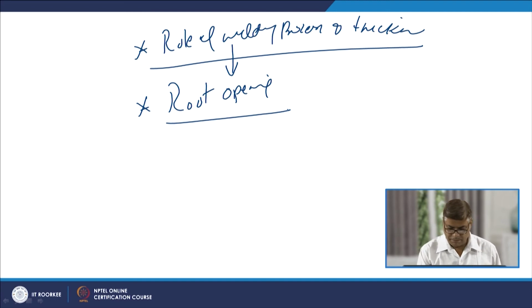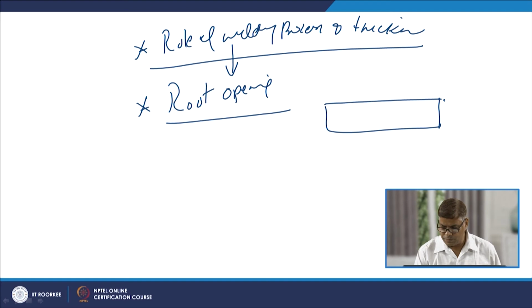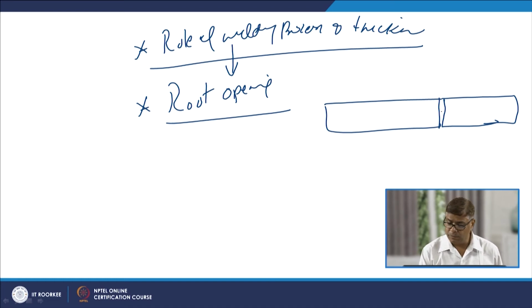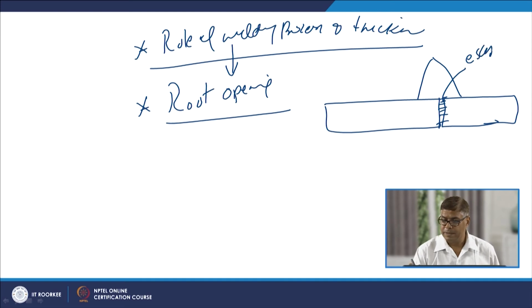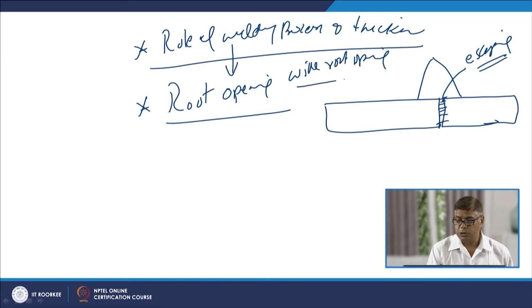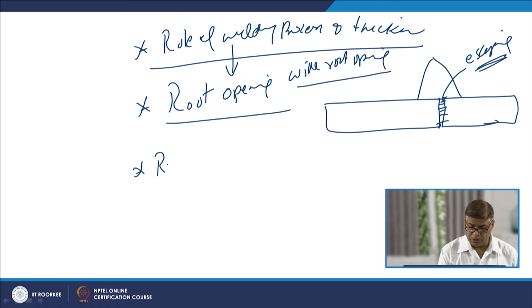This is important because if the gap is very small, then whatever zinc is there, after evaporation, will not get time to escape. So, escaping of the zinc vapors is restricted when the root opening is limited. So, it is always preferred to have a wide root opening, so that the zinc which is evaporating gets enough space for escaping, so that associated problems like the pores due to the zinc vapors can be reduced. Next is the joint restraint.